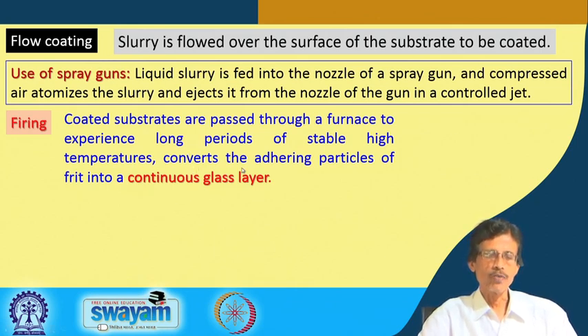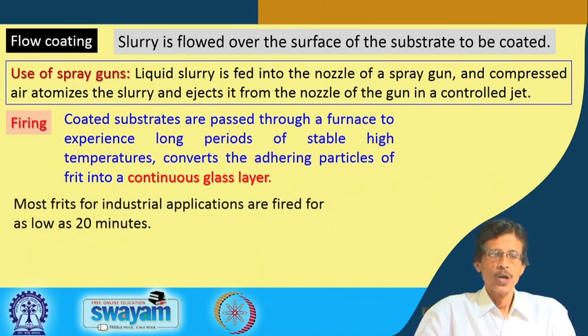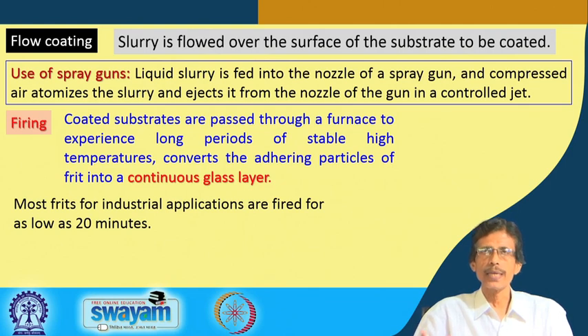So, keeping that particular material in the furnace leads to the adhering of the particles of the frit into a continuous glassy layer. From those particles of frit powder, after the molten condition, you get a continuous glassy layer. So, basically what we are getting? We are getting a molten glass-like enamel material on the surface of a not very good quality object, that is your cast iron container.